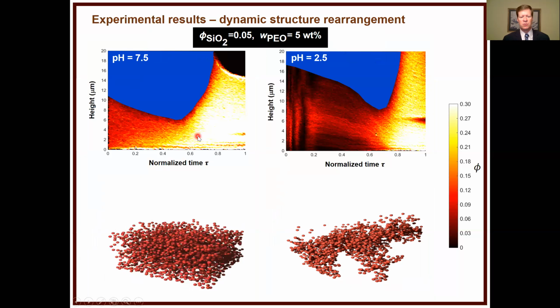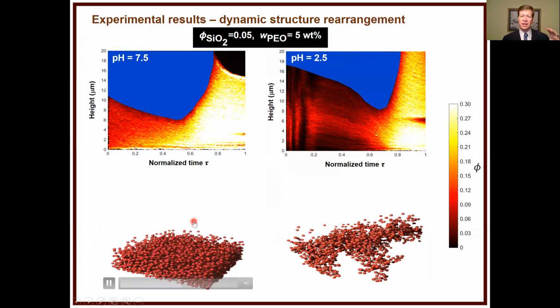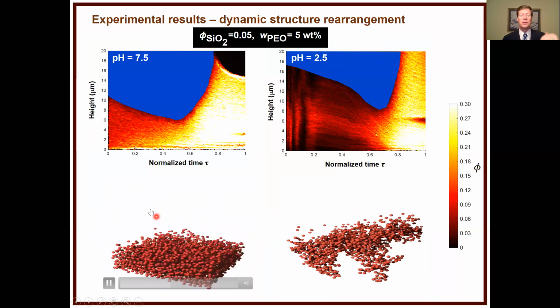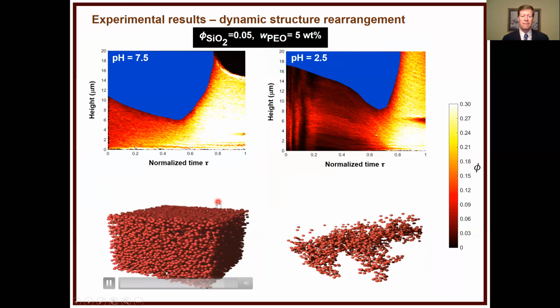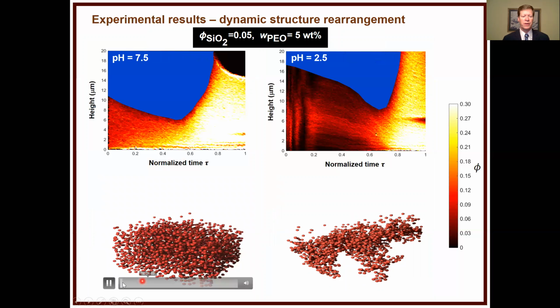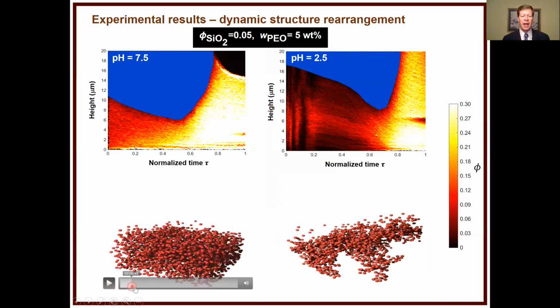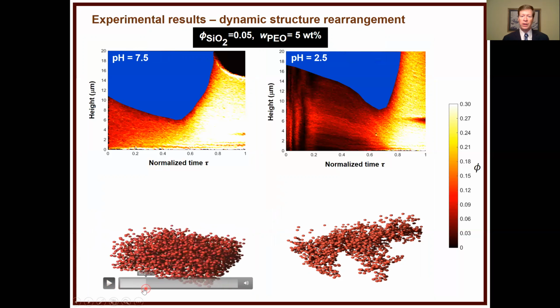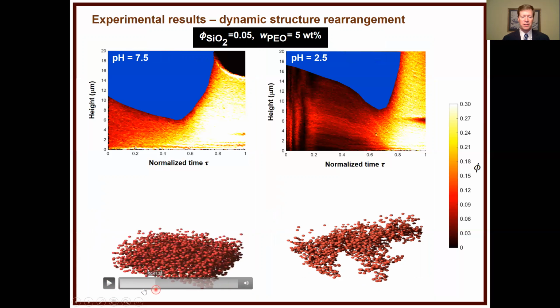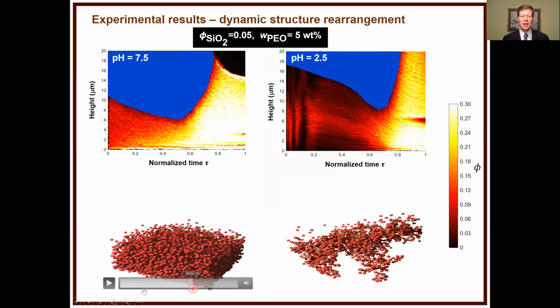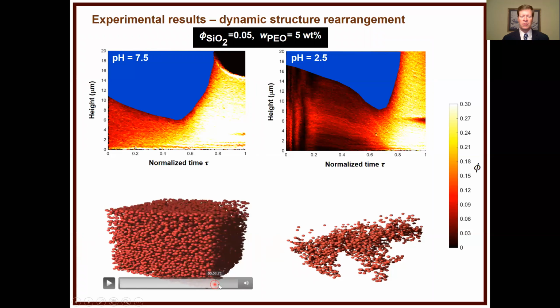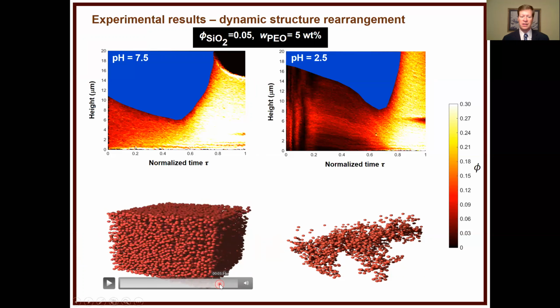Just to give you some of the dynamics that occur here, for pH 7.5, the video is located on the left. The only reason it looks like a shorter film at first is because we can't scan as deep. But eventually you can see the top surface come into view. First, particles are moving what looks like randomly, and they're actually flowing very quickly in this frame, except for the particles near the bottom. Later, as the suspension viscosity gets so high, you can see the flow velocities, track the particles, and look at the final microstructure.